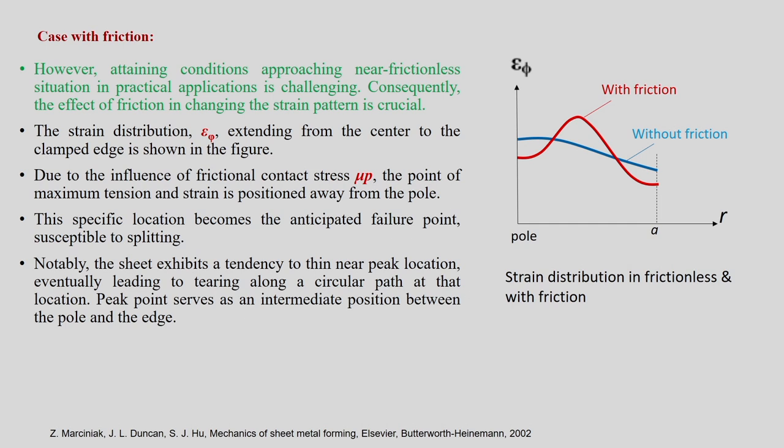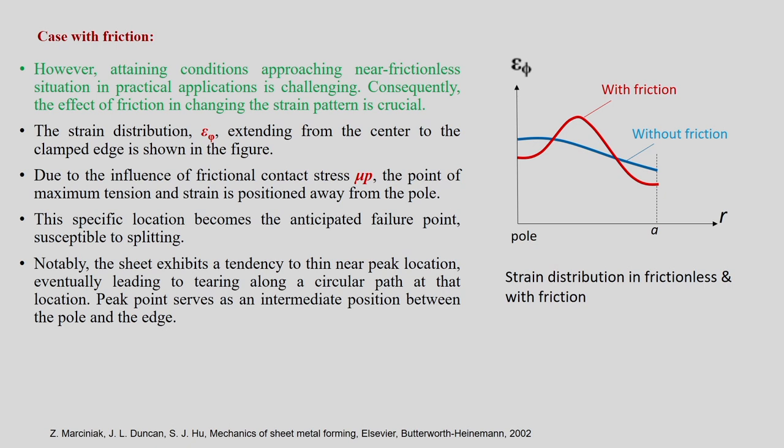Now, this frictionless case is a little impractical actually. There is going to be friction, whatever lubricant you put. It is going to be challenging to keep it frictionless. Otherwise, one has to go for the hydrostatic bulge type. So, the presence of friction may change certain strain patterns, the strain distribution in the sheet, which is very crucial for us to know.